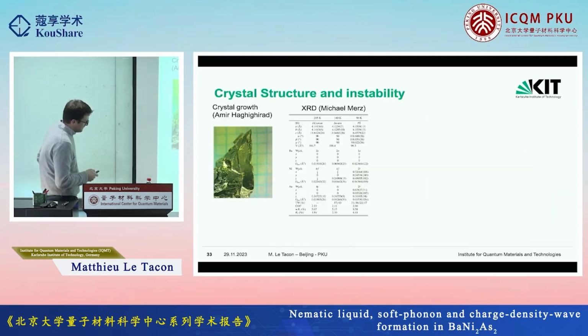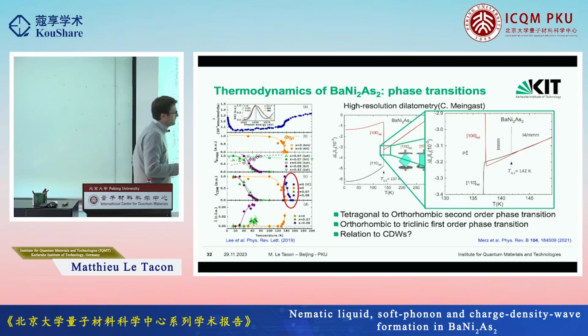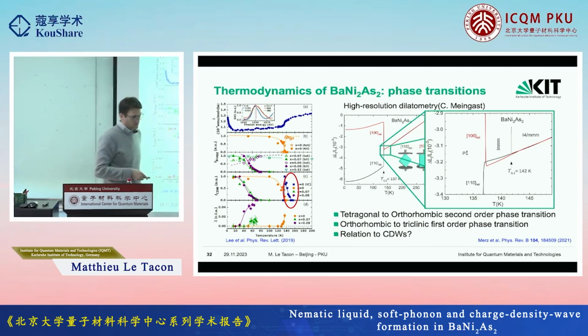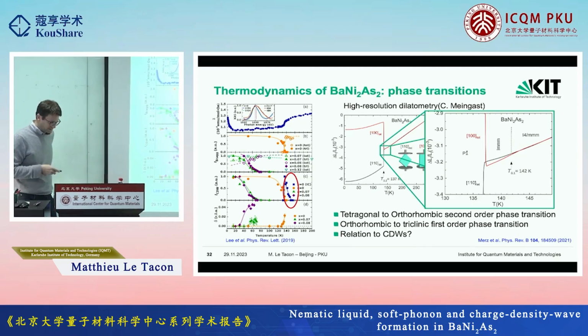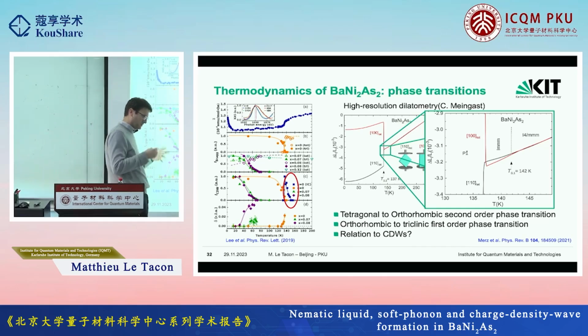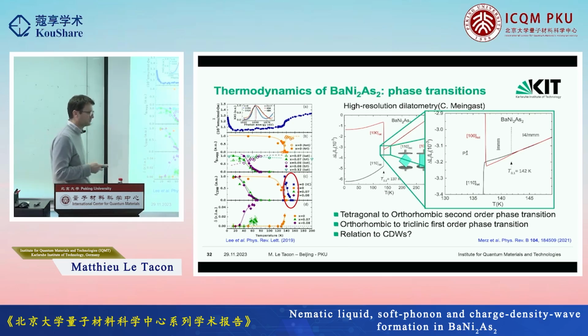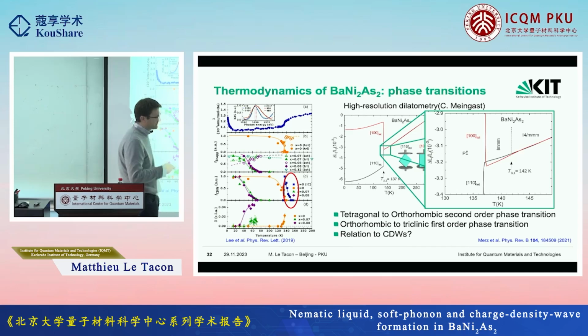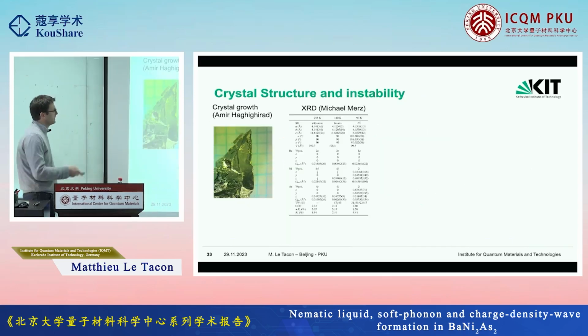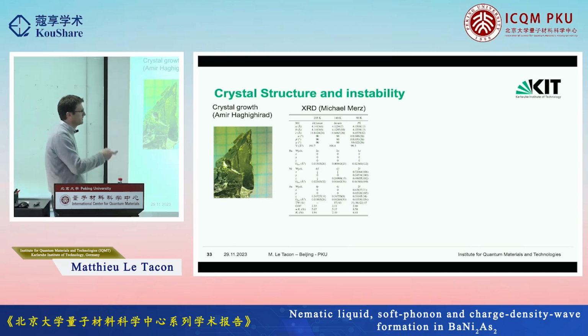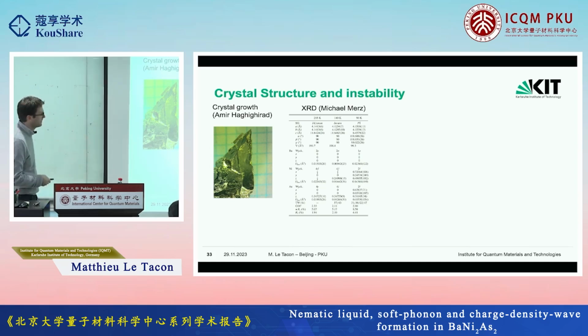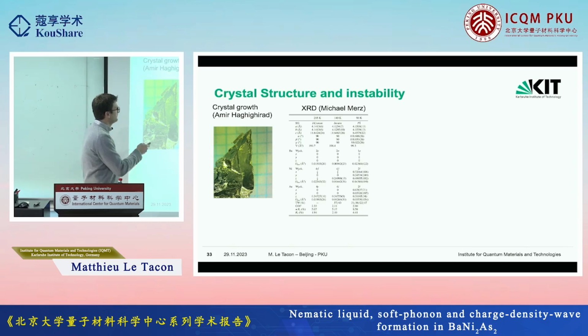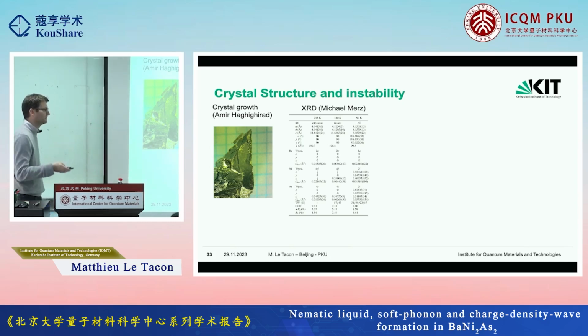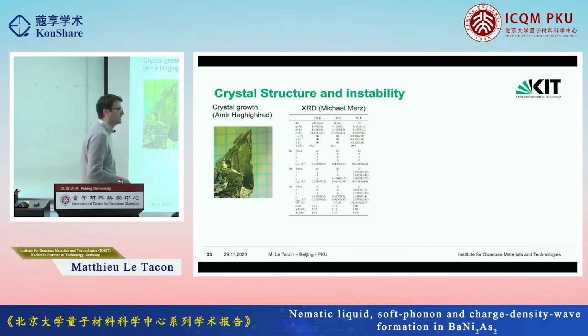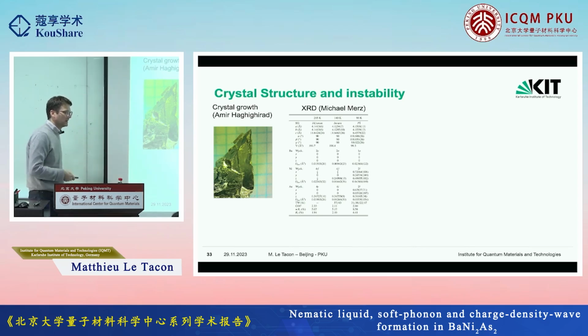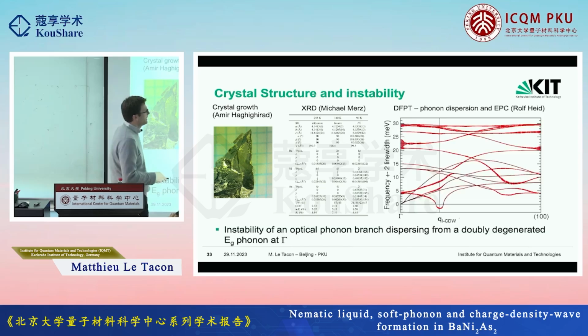One thing that had been overlooked in the early studies: people have early on been calculating the phonon spectra of this compound based on DFT calculation, but you know that with DFT you overbind a bit and you tend to have a crystal structure which is a bit too small. And when you do that, you basically don't see any instability. Now, as part of our procedure here, we determine experimentally the lattice parameter, and we like to provide our theory colleague Rolf Heid this crystal structure for the calculation. And then he can run his DFT calculation of the phonons based on the actual lattice parameter that he can relax. And that usually gives an excellent agreement with the experiment, and that's what he finds.